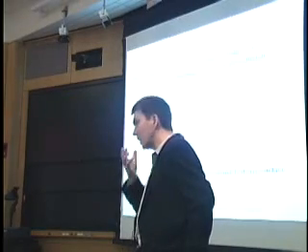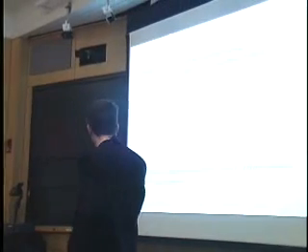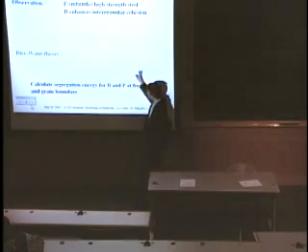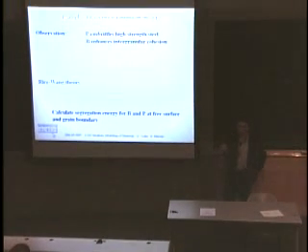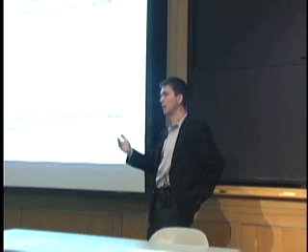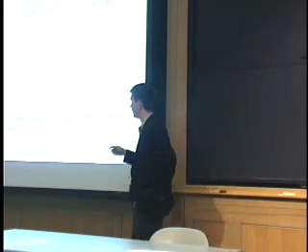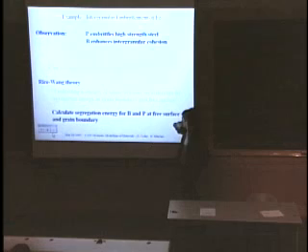But there's a very basic theory that tells you there's a much simpler way to understand this. And that's the Rice-Wang theory, which essentially states that the embrittling tendency of a solute depends on the difference in segregation energy between the segregation energy for that element to a grain boundary and to a free surface. This is actually mathematically justified. It's a quite elaborate theory that you can catch in 2 sentences.